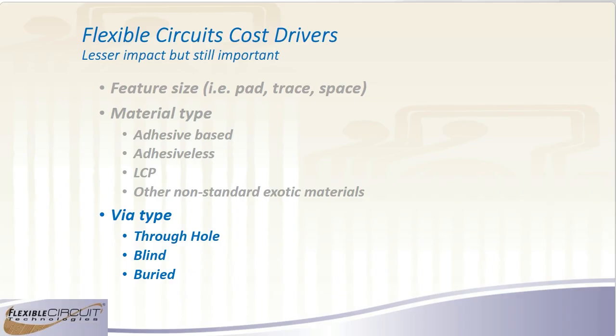When you start having buried vias or multiple layers of blind vias internally, that can drive up your cost quite a bit because now you'll have sequential laminations where you're basically going to start on your internal layers, do a drill, a plate, a print, develop, etch, put on another layer of copper top and bottom, and start the sequence over again. Each of those sequences, you're going to have additional yield fallout, and you're using very expensive equipment because you have to be able to target and laser drill based on where your targets are. So it does make the circuit a lot more expensive.